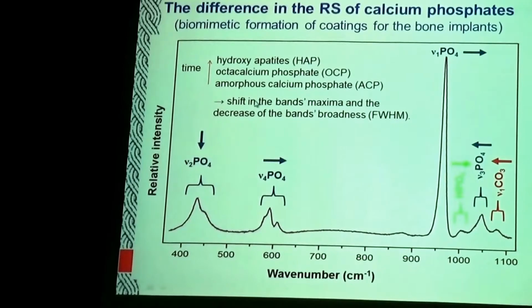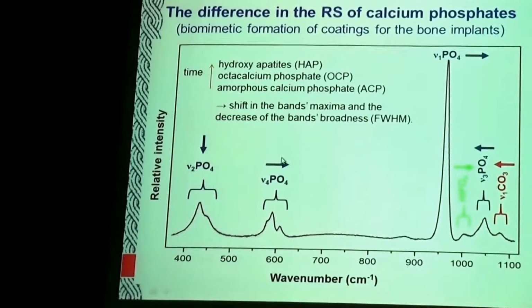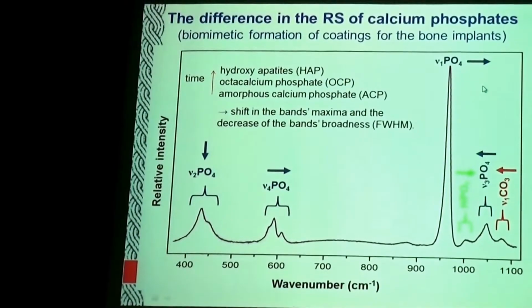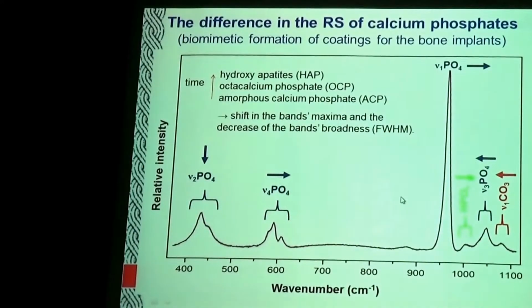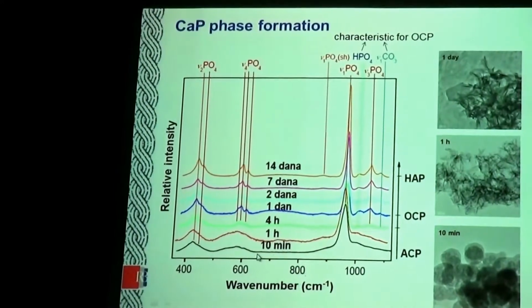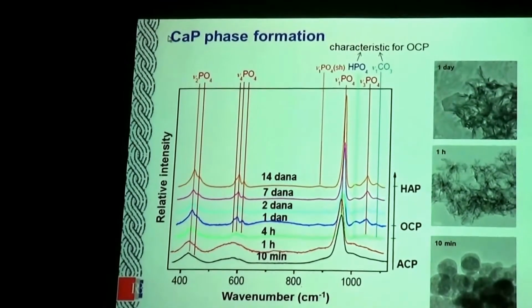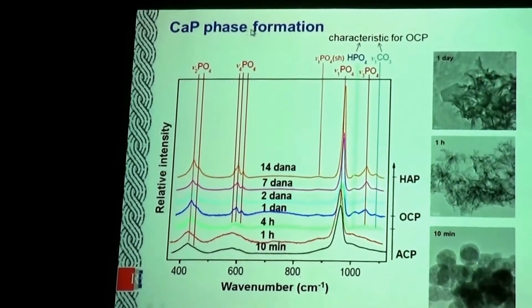If we use Raman spectroscopy, we have the shift of the band maxima and decrease of band broadening during the change of phases. This is a starting system without any addition.